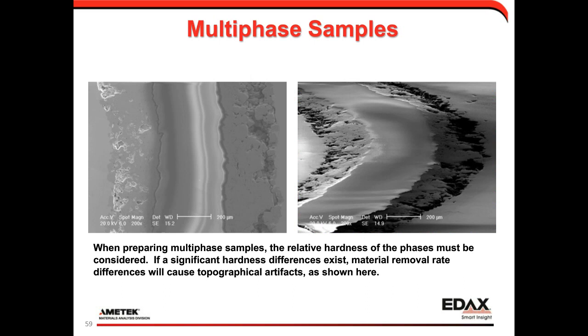Now, one of the more challenging types of samples for EBSD preparation are multi-phase samples. The reason is that when you have multiple phases, you're going to have phases that have different material removal rates. So as we polish a sample, you're going to get topographical type effects. This is just an image on the left of a copper oxide, aluminum oxide reaction region. If we're looking at it in a traditional flat SEM view, looking straight down at it, we see the layers nicely. But when we tilt it on the right for EBSD analysis, we can see little hills. That center area is higher than either material on the side, and there are little slopes going down between them.